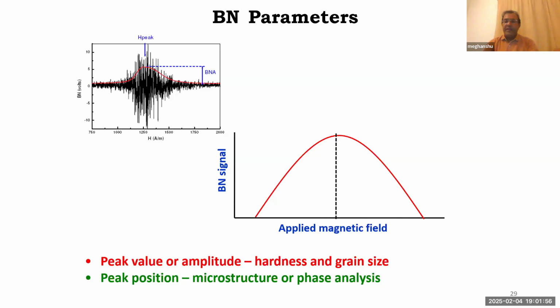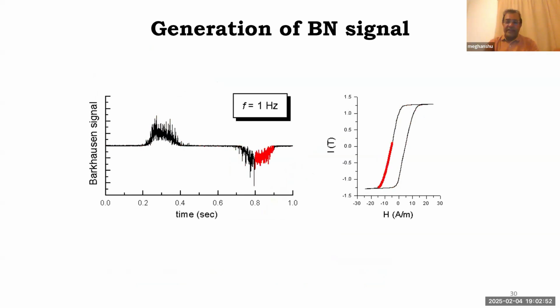In this case, the graph shows the applied magnetic field required for magnetization. So this ferrite based component has this graph that you are looking at on the screen, and it needs a certain amount of applied magnetic field as input. Now, if I apply the Barkhausen noise technique over this component which has martensite, which is hard to magnetize, then a large amount of magnetic field will be required to magnetize it. So I will get a larger magnetic field on the x-axis. So the peak position will indicate the microstructure, the phase analysis. So by using this technique, we can assess grain size, micro hardness, and microstructure, as well as residual stress.